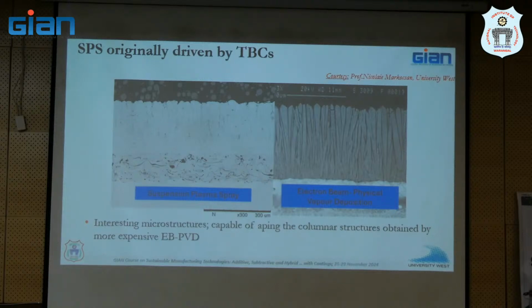Why are some groups crazy about using suspensions? They're crazy because it was soon found that you could get columnar coatings like this if you used submicron particles in a suspension. This is the main driver. It's not exactly like an EBPVD columnar coating, but it's close. It gives the same effect. What is that effect? It gives you the strain tolerance because it has this finger-like structure. So when you have heating and cooling, it can expand and contract and therefore accommodate stresses. That is very crucial in a thermal barrier coating, which sees thermal cycling. You want this to happen.